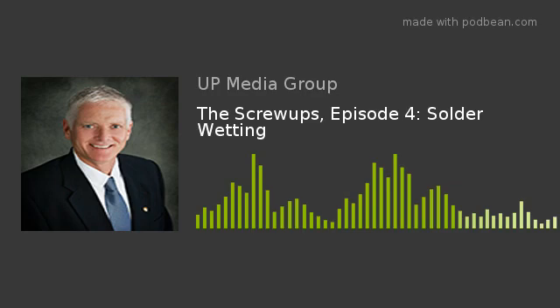We really kind of have to play investigator a little bit in those circumstances to figure out what's happening in terms of what the root cause is. Is it a handling issue? Is it a bare board manufacturing issue? Is it a materials issue on our end? Did something get screwed up during the production? So you have to ask a lot of probing questions. You have to hope that the customer is frank in telling you that, we left those boards out over the weekend and the air conditioner broke and it was 100 degrees in here for a couple hours, but now help me fix it. As opposed to not sharing pieces of information that are critical to us making an accurate diagnosis.